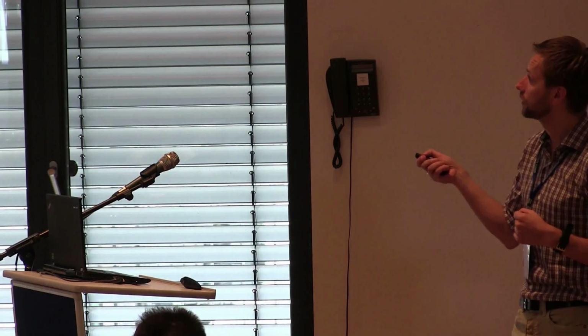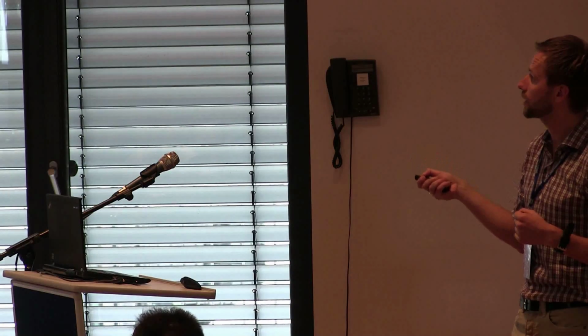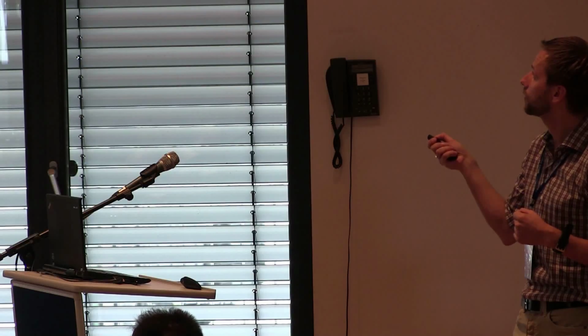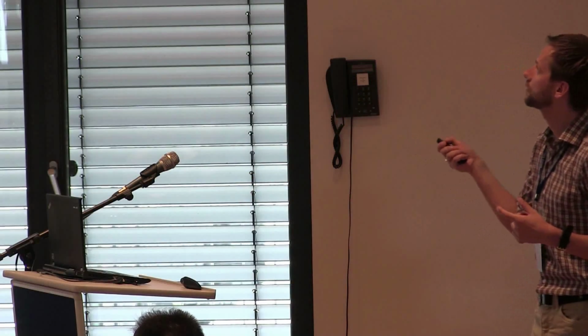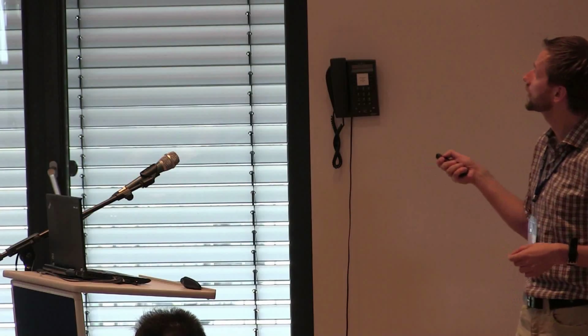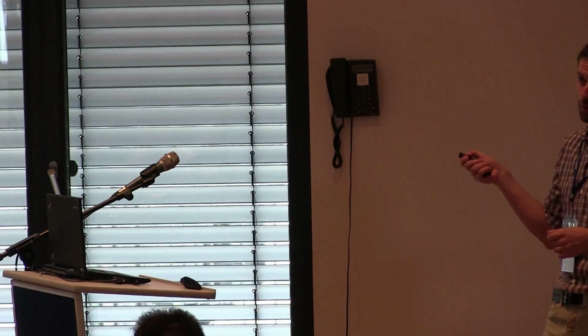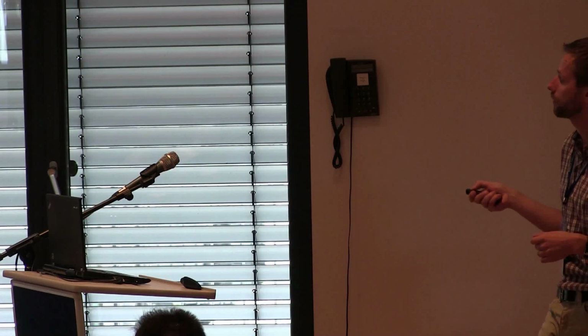So the distribution for cold electron in graphene is shown here by the blue line. There are two conductivity channels. There's intra-band conductivity in graphene, that's the conductivity of the states around the Fermi level, and inter-band conductivity like in normal semiconductors, band to band. And for the energies below the Fermi level, they are Pauli blocked. Yeah? That's why there's this dip.